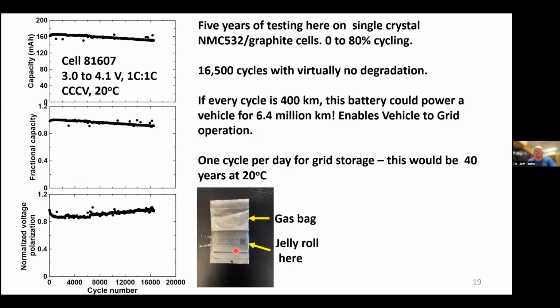Another thing that's really interesting is in our little cells, they have what's called a gas bag on the side. Now, a real lithium-ion cell would have this cut off and the cell would be sealed right here. But this gas bag is really interesting because as the cells undergo these unwanted parasitic reactions between the electrode materials and the electrolyte, some of the reaction products can be gas, and the gas bag will puff up. So it's kind of like a canary in a coal mine. It tells you when there's a problem with your cells. If you start to see the gas bag puffing up, it means that you have these unwanted reactions going on.